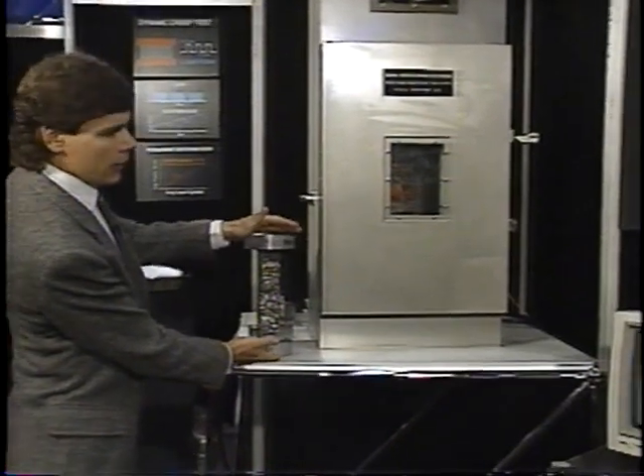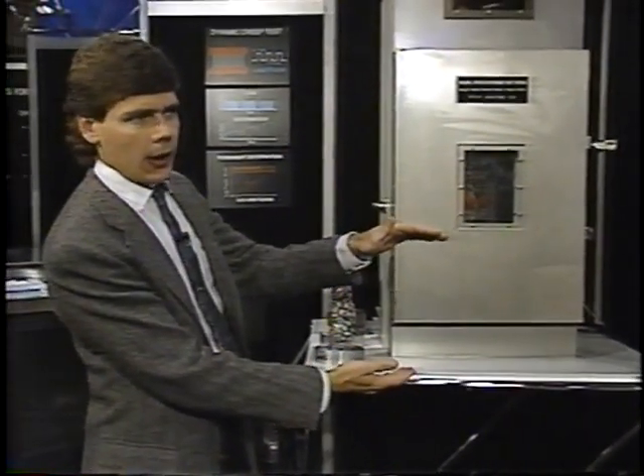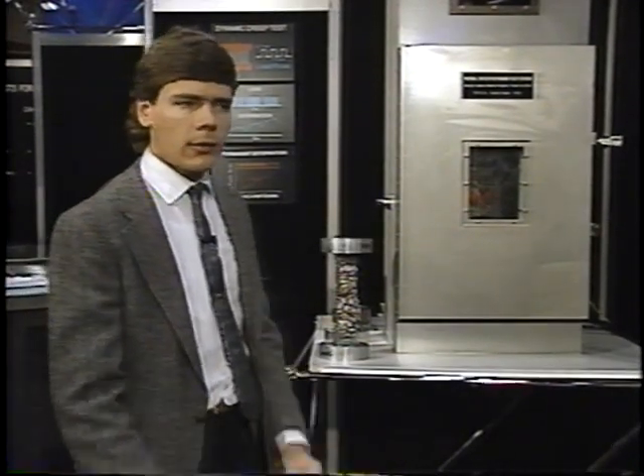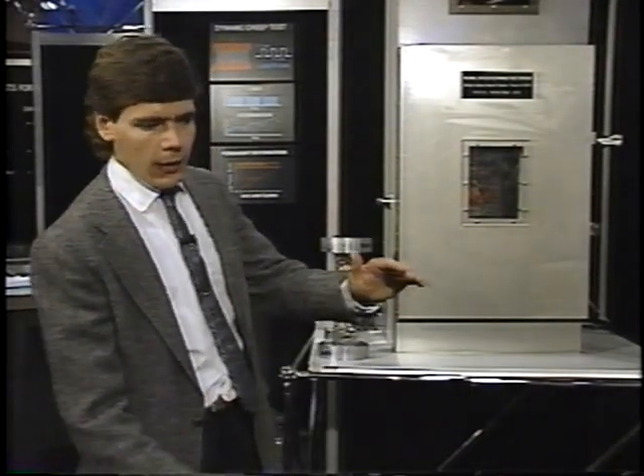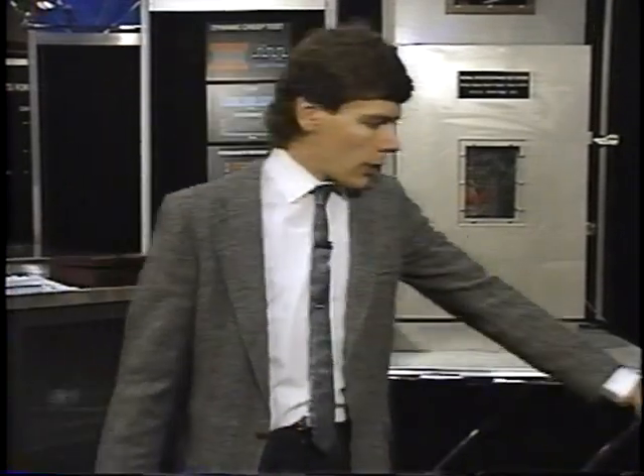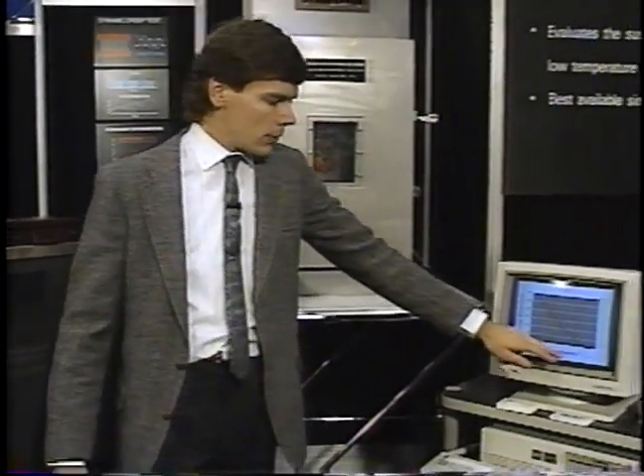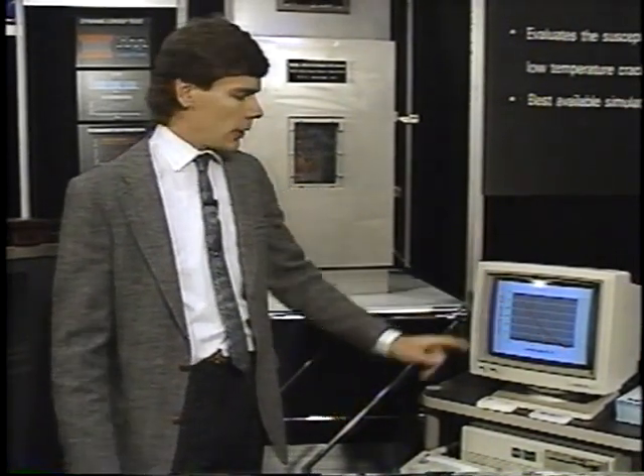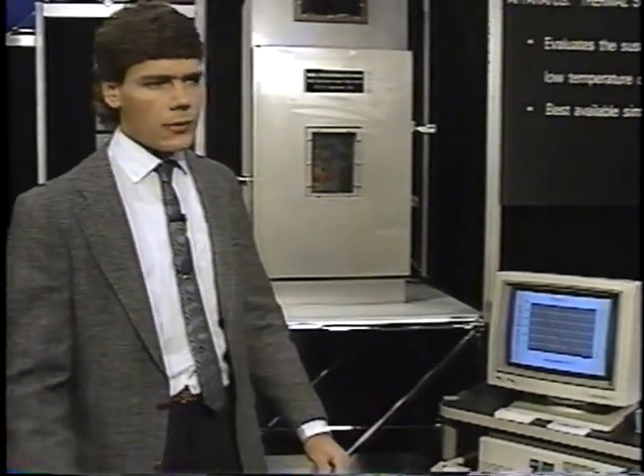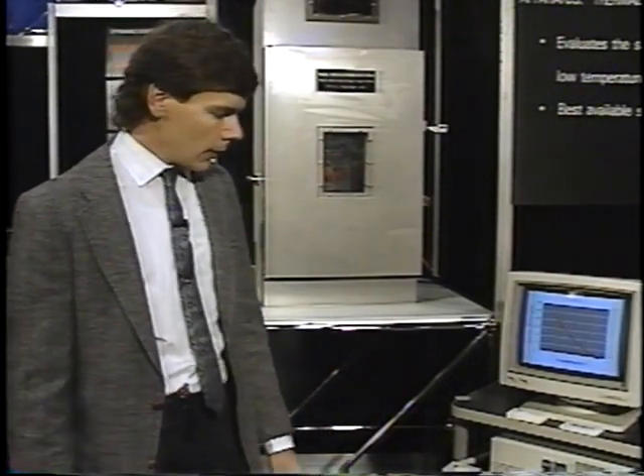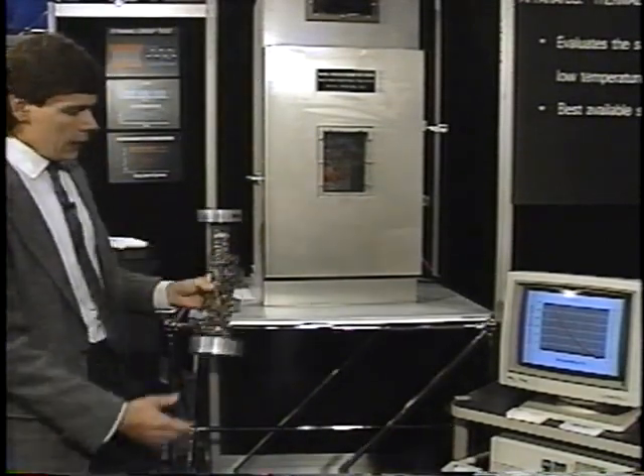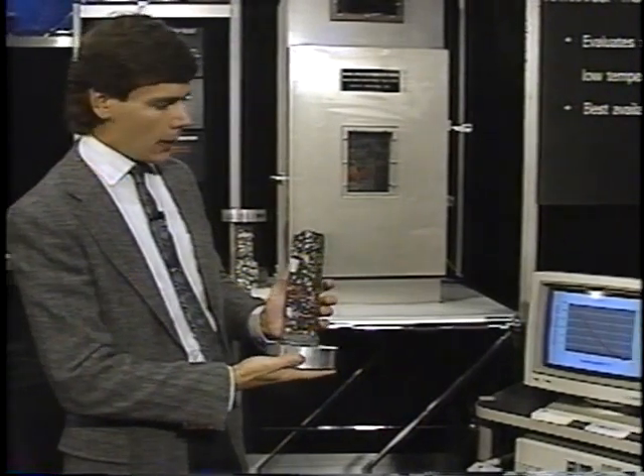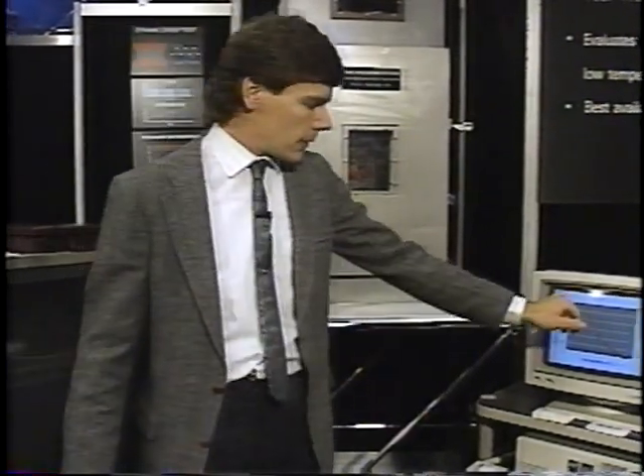What that will do is, the specimen tries to contract and we pull it back to its original length. As we cool the specimen more and more, we have to pull on it harder and harder. So the general trend of the test is that as the temperature cools, the load increases until eventually we get to a point where it fails - the load on the specimen has reached its tensile strength and the specimen fails. We take each specimen all the way to failure, and what we get out of the test system is load at failure as well as temperature at failure.